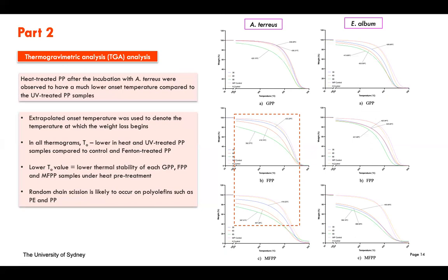So this indicates the onset temperature. We extrapolate this onset temperature to denote the temperature at which the weight loss begins. For the pristine polypropylene, the onset temperature will be much higher. For example, the onset temperature for the control will be around 430 degrees Celsius. After 90 days of incubation with the fungi, you can see that the onset temperature starts to decline. So it reduces the thermal stability of this polypropylene.